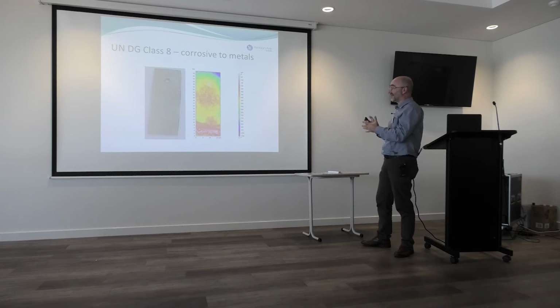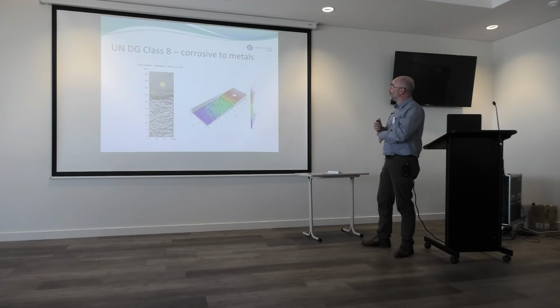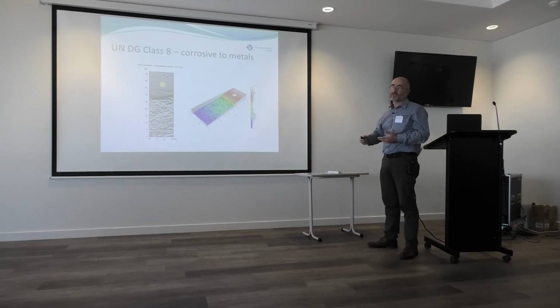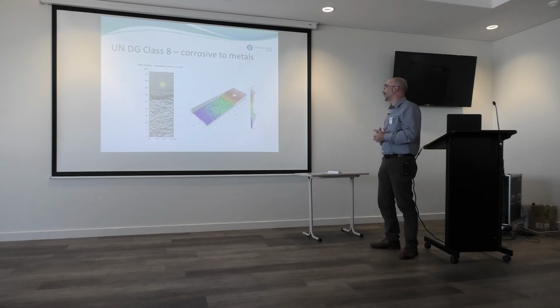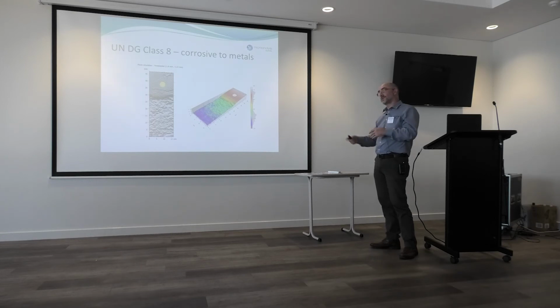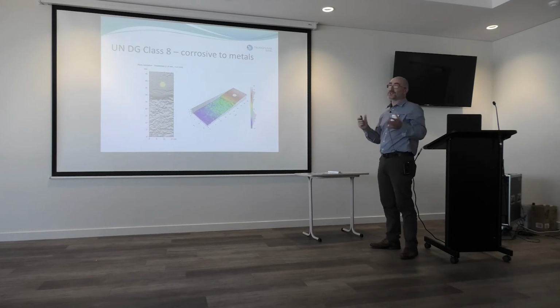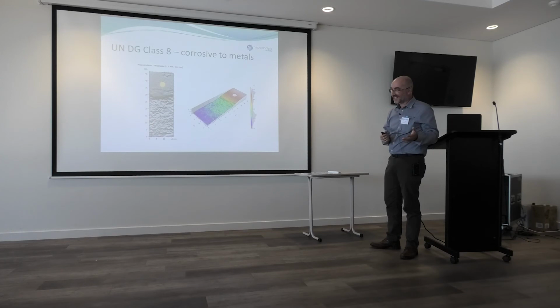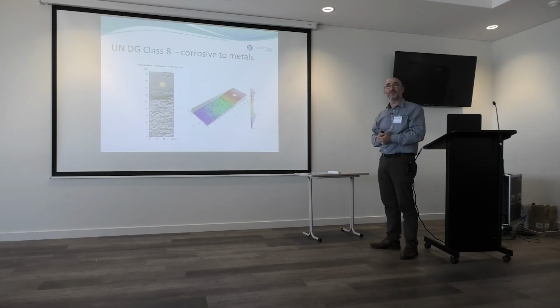We were getting a lot of feedback, and they were wanting a lot of mixes made up. We were adding lime to various samples to see if we could control the corrosion. One of the things we noticed in some coupons was that there was so much surface loss that we were not able to have a reference point. If there was nothing of the original surface left, how did you actually know how much loss had happened? And clients who were getting other tests done were sending samples off to other labs, and samples like this were coming back as a pass. So there were a lot of mixed messages depending on how people were ascertaining what a pit was. Everyone started arguing about what a pit was after that.